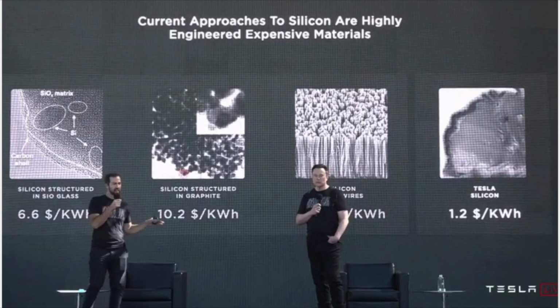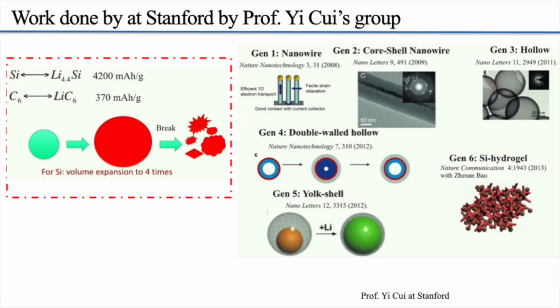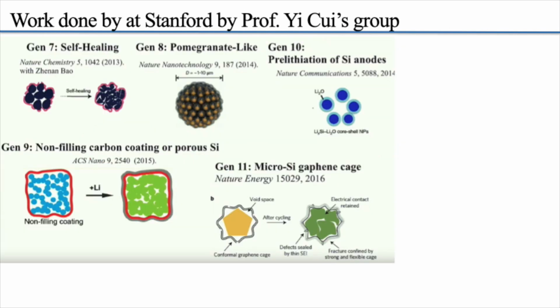So back in 2008, they started with nanowire architecture, and then core shell, hollow, double wall hollow, all of these. But the problem with all of these is that you can't scale these technologies really fast and to really high quantity at desired economic levels, like $100 per kilowatt hour for the whole pack. That's just impossible, because the manufacturing of all these anode materials costs a lot more. And then they kept improving. They did self-healing, so if it expands and breaks, the polymer coating on the outside keeps it together. And they designed pomegranate-like structures, non-filling coating, and finally micro-silicon graphene cage using graphene. But all of this is quite hard to scale up.